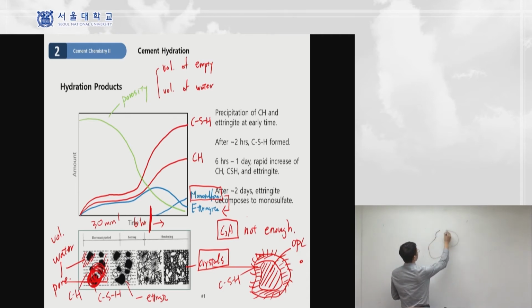So let's say this is one cement particle, and this is a combination of C3S, C2S, C3A, and C4AF, obviously, and also gypsum. Right? They are mixed together. This is one cement particle, and all these are water, right? So this cement particle is surrounded by water. So there is a formation of this calcium silicate hydrate. This is also kind of needle shape. And this is calcium silicate hydrate, and this is dense phase, dense. Okay. Because it has a strength, right?